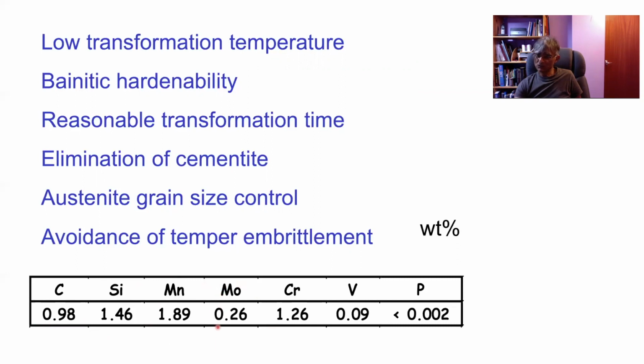We want to make large quantities of this material, so it will inevitably contain impurities which segregate to the austenite grain boundaries, for example, phosphorus. And we do not want that because strong steels become brittle at the boundaries if there are impurities. And the addition of molybdenum cures that problem by gettering the phosphorus. And this is again a hardenability addition.